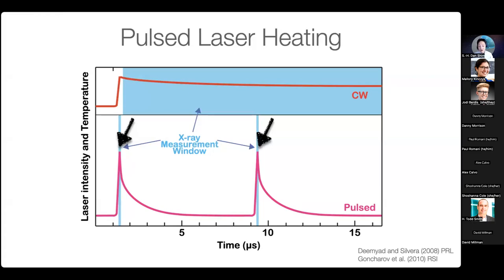And in fact, many people in our high pressure community have worked on this problem in the last decades, and they found a very interesting solution, which we adopted into our experiment, which is to heat the hydrogen-bearing sample for a very short period of time, like microsecond range. That allows us to prevent hydrogen from having enough time to diffuse into the diamond so that we can protect the diamond and reduce the possibility of failure during the laser heating. And by accumulating or repeating this process for hundreds of thousands of times, we can do heating for a total of 1 second or more.